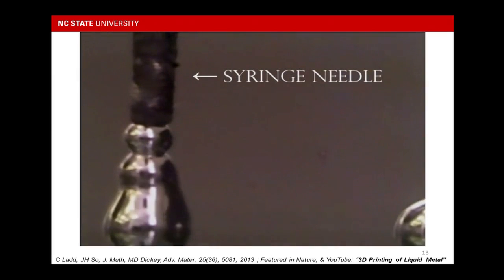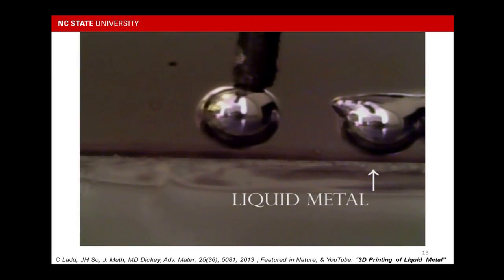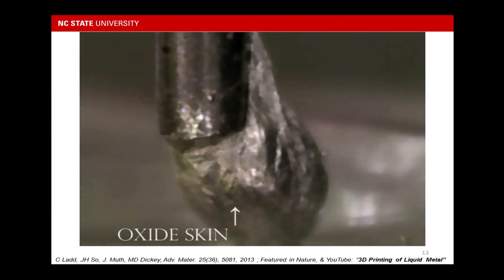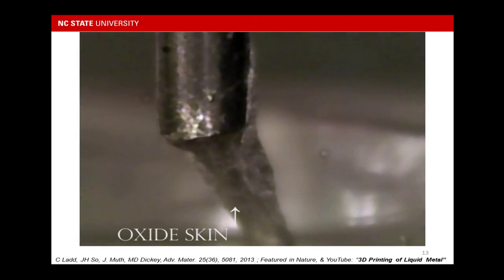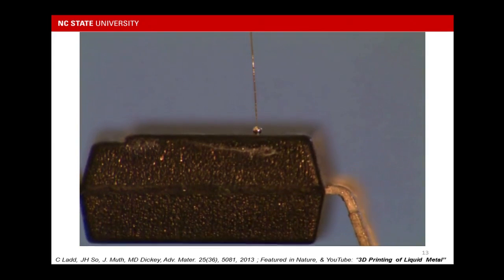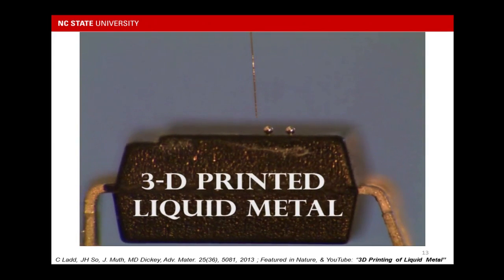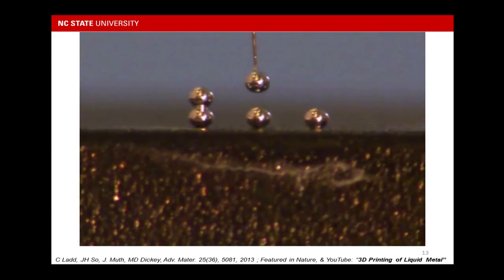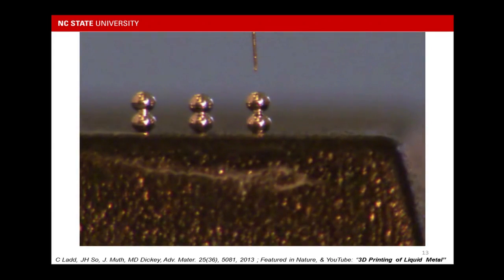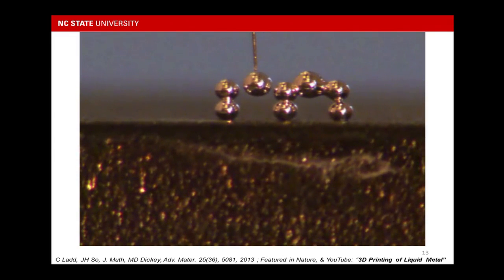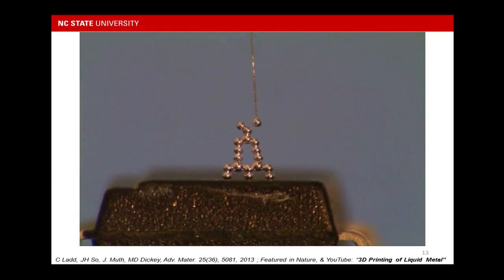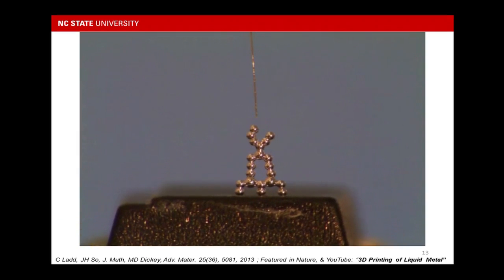One thing we can do using this liquid metal is 3D printing. As you see here, we can 3D print this liquid metal droplet. This is the oxide skin. Because this skin has enough mechanical strength, it can hold these structures and stack them up to build different 3D structures. Now you can think about combining this 3D printing with other materials, which can be done at room temperature. In that case, you can come up with many cool ideas.